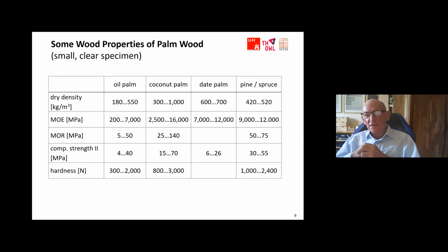The next slide gives us an introduction to the properties, in density, in MOE, MOR, and so on. I don't want to go into detail. The only thing, if we compare on the very right column the pine and spruce properties with the palm wood properties, we see that if we go into the higher densities, medium and higher densities, we have similar properties compared to pine or spruce. So this gives us the information that we can use the palm wood in very different products. This is a chance, but also a challenge. And we can use it even instead of softwood species like pine and spruce, if we do it well. And so this is the challenge for us as researchers to do it well and for the industry to do it well.